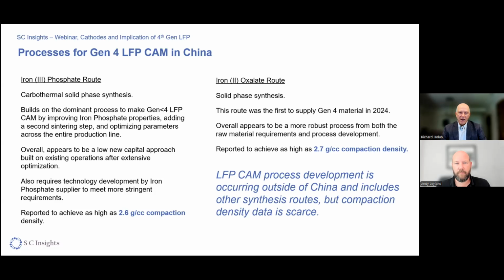Now, the iron oxalate route is also solid synthesis, but this route was the first route to supply Gen 4 material in China in 2024. It overall appears to be a much more robust process, with fewer restrictions on the raw materials than the iron phosphate route. And it's also been reported to give compaction densities as high as 2.7 grams per cc.